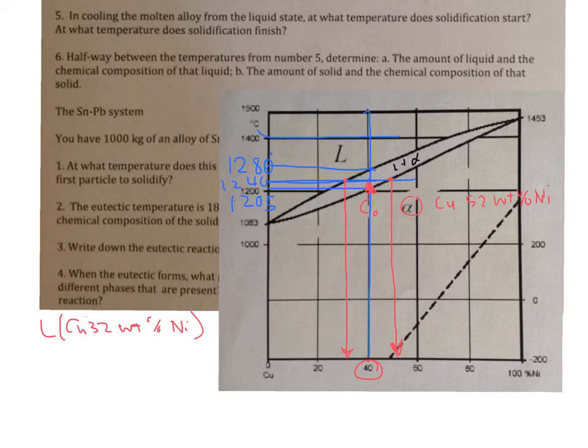Let's use the lever rule calculations, though. So we'll say the fraction of liquid is equal to, and we know on the base it's going to be the difference of the total length of this lever. So that's going to be 52 minus 32, or what is that, 20 on the bottom.